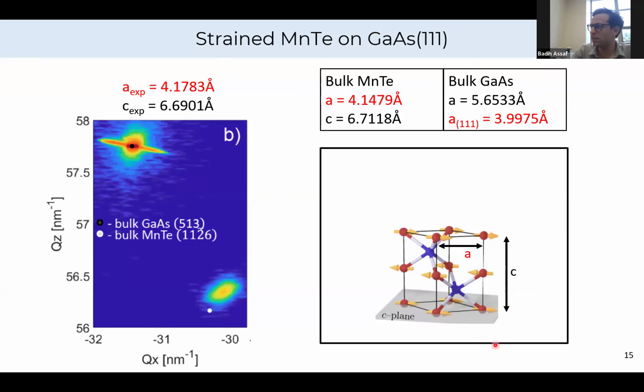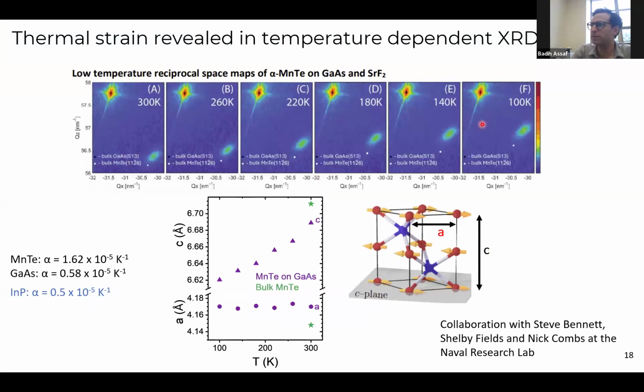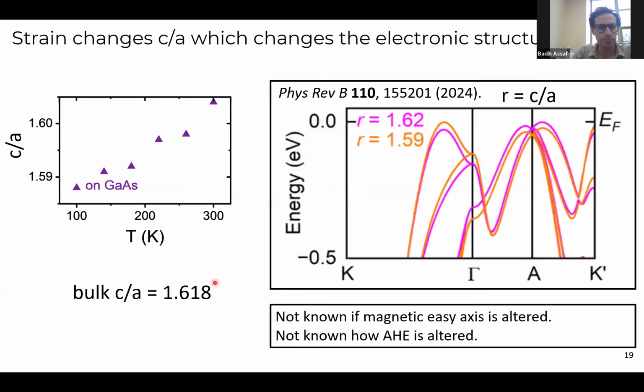So the bottom line here is that the C and A values for the lattice parameters of MnTe grown on III-V substrates are very different from what's considered in most theoretical studies and most DFT calculations on this material. We can repeat this experiment down to 100 Kelvin, with measurements done at the Naval Research Lab with Steve Bennett, Shelby Fields and Nick Combs, and we can extract the C over A ratio down to 100 Kelvin. It turns out to be lower than 1.59, whereas in bulk the C over A ratio is approximately 1.61 to 1.62.